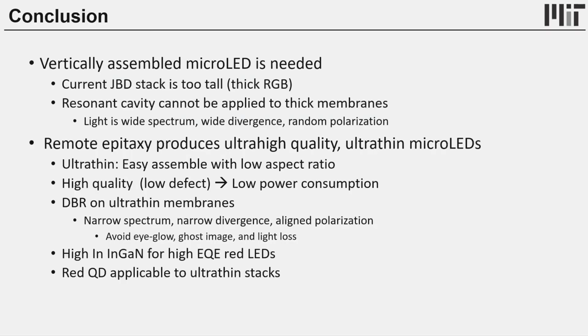So, vertical assembly of micro LED is needed. The JBD stack is pretty thick. So, also more importantly, the resonant cavity concept, which is very valuable, cannot be utilized in these thick layers. But remote epitaxy produces ultra thin, high quality micro LEDs. So then it can be easily assembled. It can be a high quality DBR, the RC concept can be applied. So then you can have the narrow spectrum, narrow divergence, aligned polarization, so that all these problematic issues can be gone. No eye glow, no ghost image, no light loss.